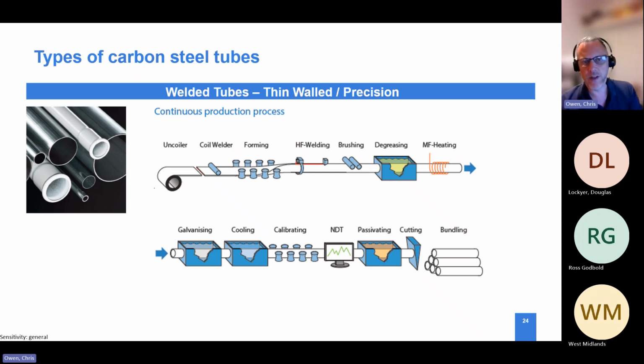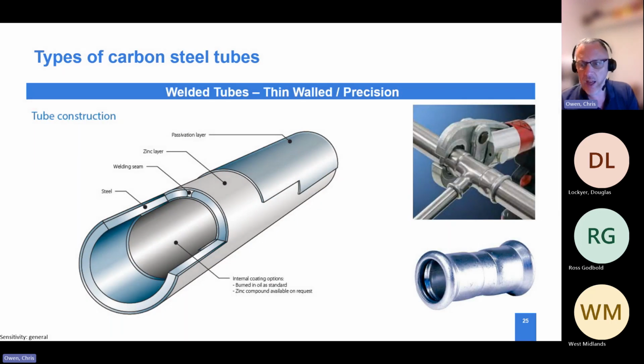But I wanted to make reference to this because, again, it's about the manufacturing processes, and the issue with this process route is that whilst you've got a continuous process and the tube is actually going through a galvanized bath, which is integrated in the flow line, so you end up with very thin wall, very good cosmetic appearance tube. The tube is still a cold formed tube, and obviously the issue associated with that is the heat affected zone is still present. And obviously, when you're deforming the tube or the fitting body, which can actually be made from a similar tube, then you're adding additional work hardening there.